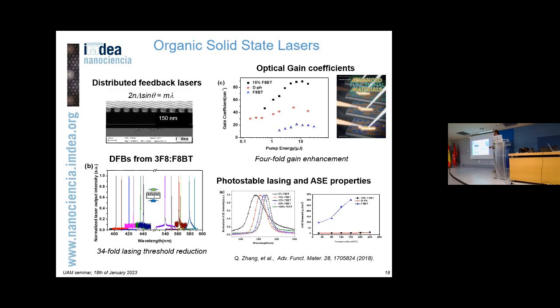So we get this, and then we simply deposit the film on top. If you deposit a very thick film, then there won't be corrugation on top of the film. That means that if you have any sort of confinement, the diffraction is going to work only at the interface between the substrate and the film, and here you have the lowest refractive index mismatch, so you do not get very efficient confinement. What you try to get is to minimize the thickness in order to homogeneously cover the grating, but at the same time have some sort of corrugation.